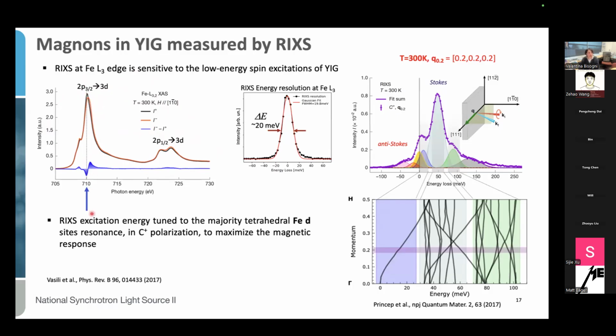And we selected the energy indicated by the blue arrow here, which corresponds actually to the majority sites, to the iron d tetrahedral sites. And we pick this resonance to maximize our magnetic response, being sensitive to the majority iron sites.